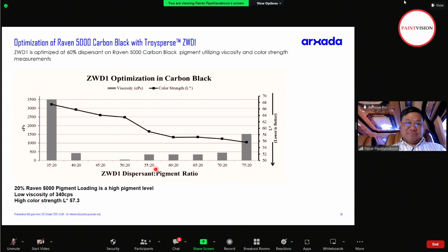The second number, right after the colon, represents the pigment loading for carbon black in the formulation that you try. For example, this one is 60% dispersant on pigment weight with carbon black at 20% loading in the formulation. So the white bar here on the left-hand side with a gray color represents the CPS, the centipoise of the pigment paste, which runs from 3,500 down to somewhere less than 100 centipoise, all right?